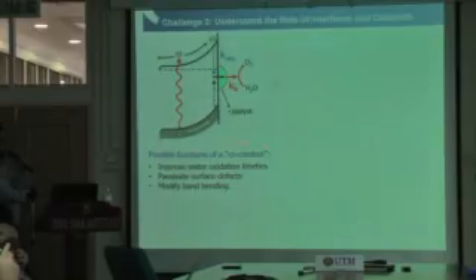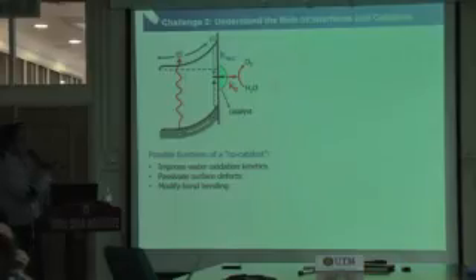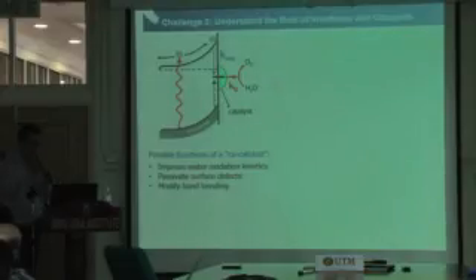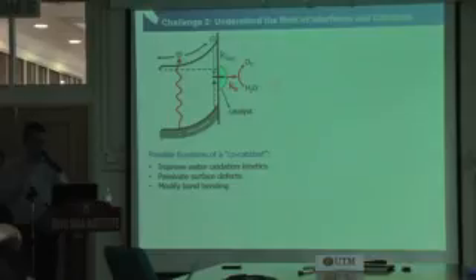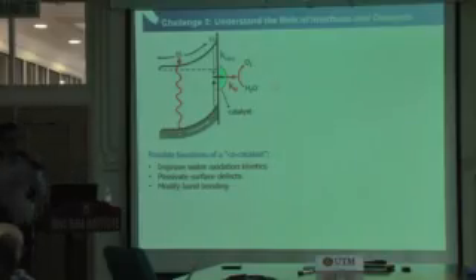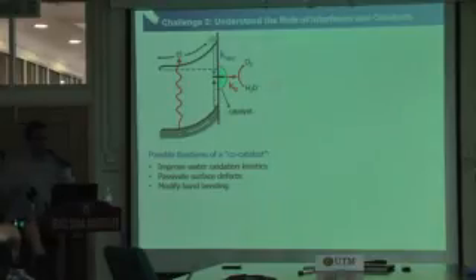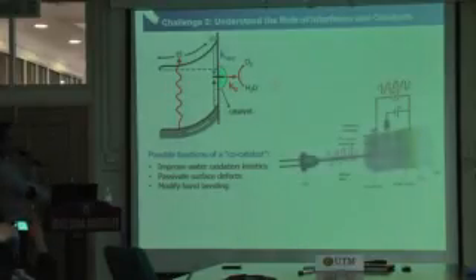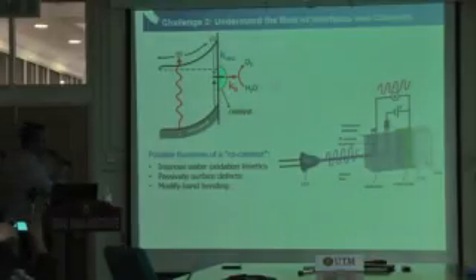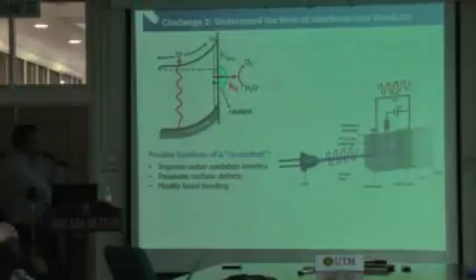So how do we now deconvolute these processes and see what really is the role of the catalyst? We think that it is important because so far we have been looking at this from a trial and error perspective. When we look at the literature, we see that this catalyst is a good catalyst. We zap it onto our metal oxide materials and hope that it will do the same thing. But often, it's actually not the case. We hope that it's going to work with our material as with the others, but often it's not. So if we understand this, it's going to help us in designing these metal oxide catalyst combinations in the future. So in order to understand this, we resort to a technique called intensity modulated photocurrent spectroscopy.